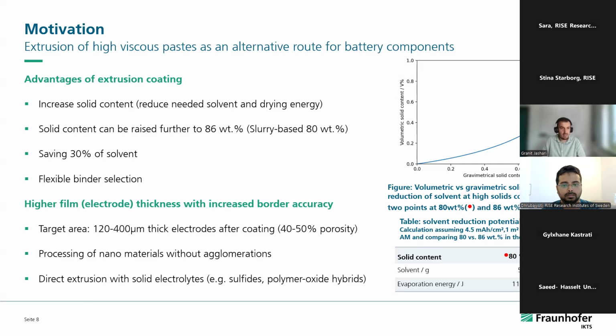Therefore, we developed the semi-dry extrusion process, where we can really increase the solid content. So we reduce the need for the solvent, which means we also reduce the drying energy to dry the electrode. With that, we would save around 30% of the solvents.